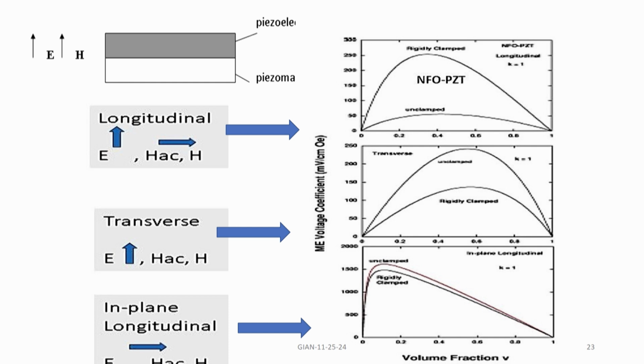What is given here is the magnetoelectric voltage coefficient under two conditions. One is the bilayer is free, or the bilayer is clamped with an external force. You can take, for example, a bilayer and then clamp it with a C clamp, or any type of mechanical force to squeeze it, or you can do it with just putting the composite between two fingers and then make sure that it doesn't have the power to expand or contract in the perpendicular direction.